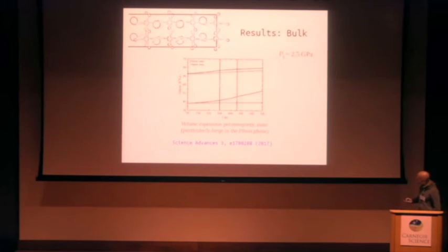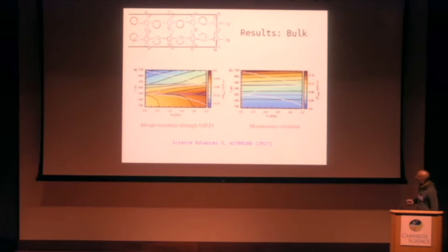So, sorry, this was just for the particular case of fixing the temperature to 2.5. In this region of the phase diagram, we find this peculiar reentrant phase. But we did the same for all the ranges that we studied. And again, this is the Helmholtz free energy difference between the orthorhombic and the tetragonal phases.